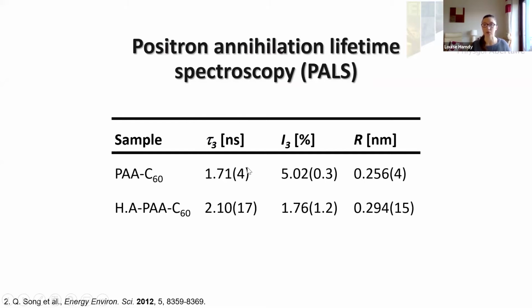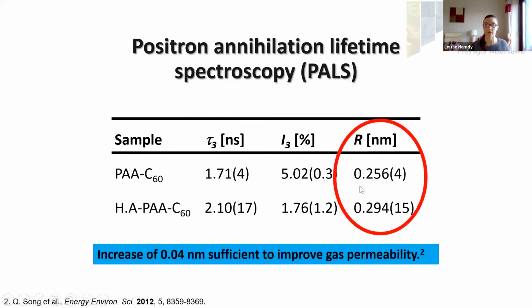For PAA-C60, we see a lower lifetime of this orthopositronium state, and we have a lower radius of free volume. And the hydrophobic additive material has a radius of about 0.04 nanometers larger than the non-hydrophobic additive material. We had a look at some other research and have found that indeed an increase of just 0.04 nanometers is sufficient to improve gas permeability. And this is the origin of our enhanced CO2 uptake.